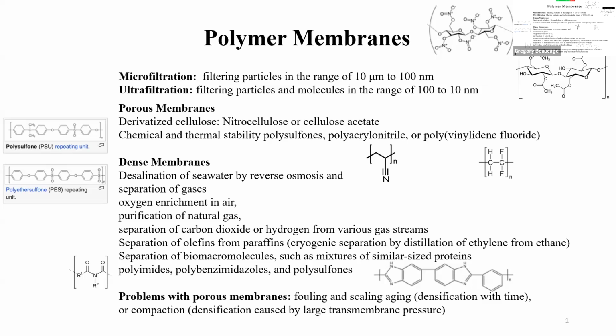Yeah, and you can almost use a group contribution method, just figure out the del solubility parameter and find something that matches it. There are tables of solubility parameters, and you can calculate the chi parameter from it, right? The difference of the del squared gives you the chi parameter.